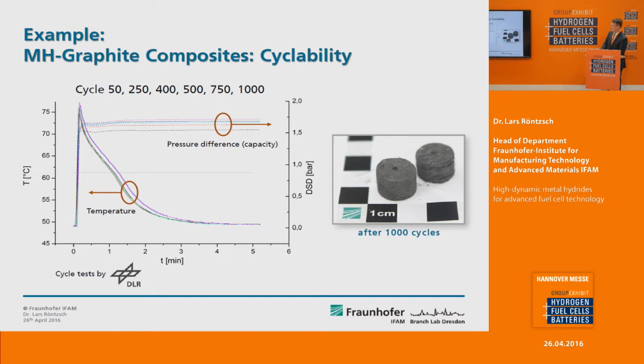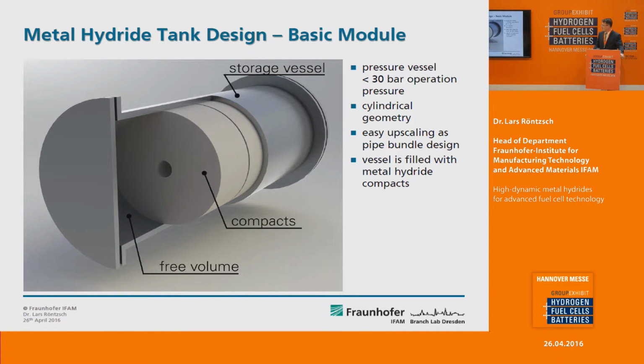In this case, it's a collaboration with our colleagues from the DLR in Stuttgart. We have shown that over 1,000 cycles, the material is practically stable, and you can imagine that a technical readiness level has been reached for this high dynamic metal hydride storage device.